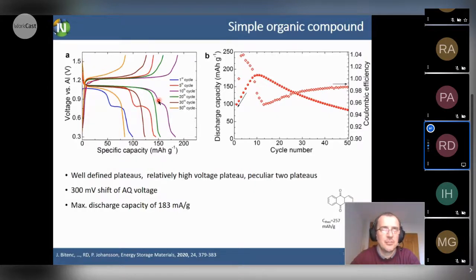voltage disappears. And just considering the voltage difference between lithium, magnesium, aluminum, we would expect a voltage around 0.8 volt, not around 1.1 volt. So the question was why we have this 300 millivolt shift, and also why we have 2 plateaus.